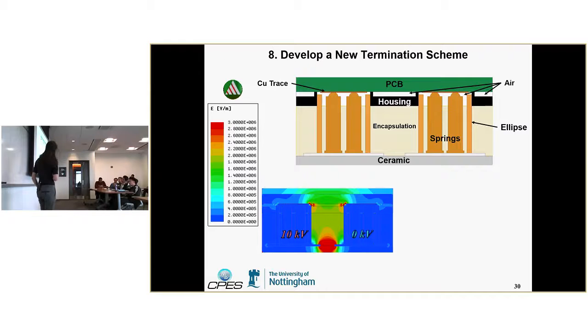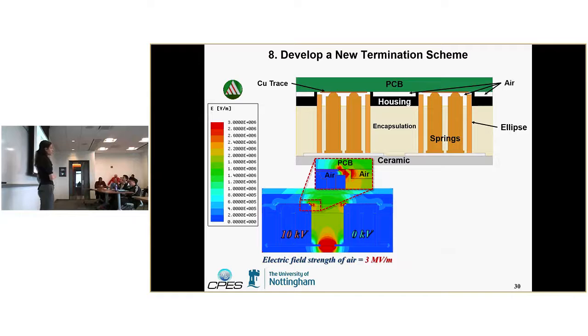So we again looked at electric field simulations. If you have 10 kV between here and here, you can see internally, because of those springs, there's not a lot of significant electric field. But still in these air gaps you have some high electric field that exceeds the breakdown field strength of air. So we looked at some field grading methods.